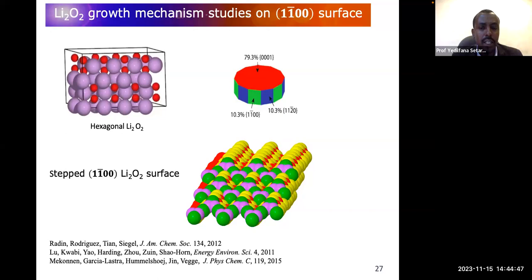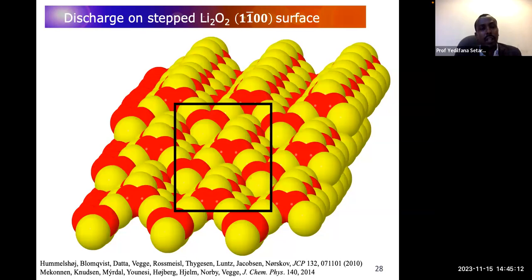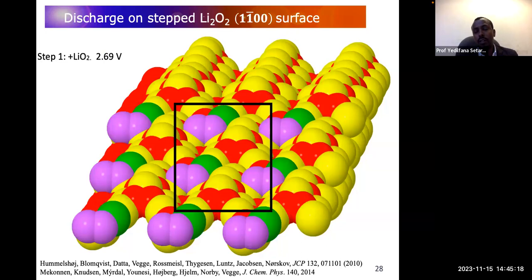This is, I think, a 3 by 3 surface of 11 bar 00. And we want to see how the lithium oxide is growing on the surface of this 11 bar 00 facet. So this is my surface. Now I check if the first step is either adsorption of lithium, or adsorption of oxygen, or adsorption of lithium superoxide, or maybe other species.